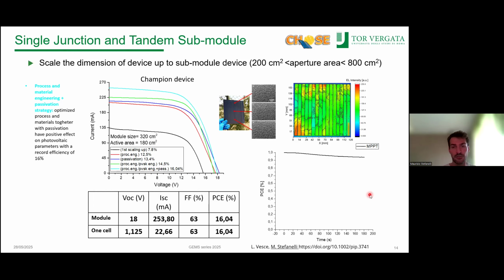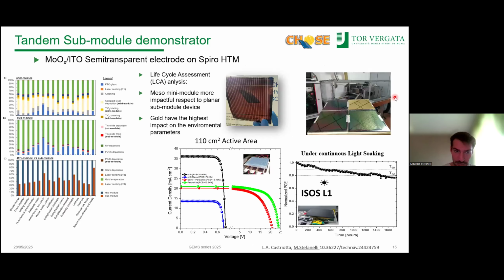We obviously assessed the uniformity of this module with different techniques, morphology techniques, and also EL measurement to understand visually on the modules where and how the cells behave. And of course, also the stability is something that we addressed. We also used this kind of fabrication to do a life cycle assessment analysis. And of course, the most impactful process for the NIP structure in this case is the gold evaporation, first for the high cost of the raw material, and also for the high cost of the process with the high vacuum evaporation. Of course, the low temperature ETL also has less impact than the high temperature ETL, and for this reason, also to avoid the gold electrode,